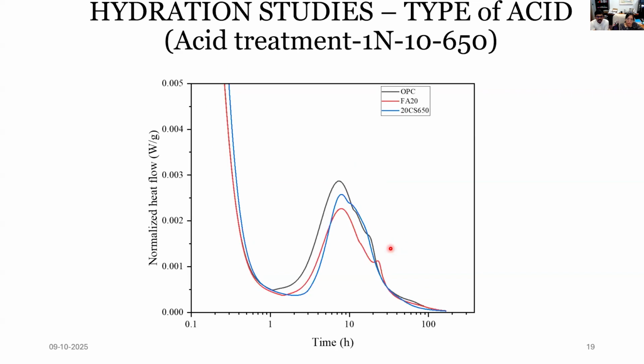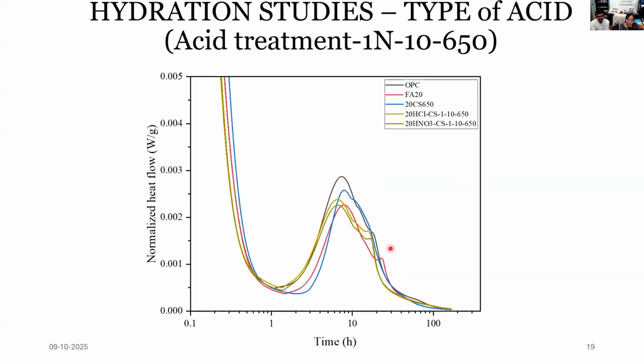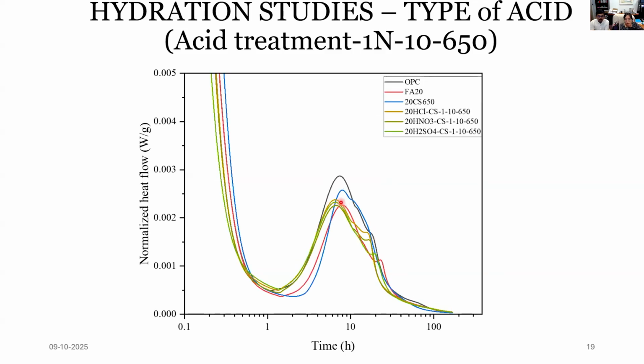So if this happens, we should be careful about using sulfuric acid as a pre-treatment method, because the ettringite formation, the sulfate depletion peak, shifts to a higher value, which means that the ettringite which is forming in the system is forming at a delayed period, which might lead to soundness related issues. So that may cause problems for hardened properties and durability related properties in the future course of time. And when it comes to using the calcined ashes at 650 degrees centigrade, we could see that the pattern is almost similar when we are using the treatment with different kinds of acids like hydrochloric acid, sulfuric acid, and nitric acid.